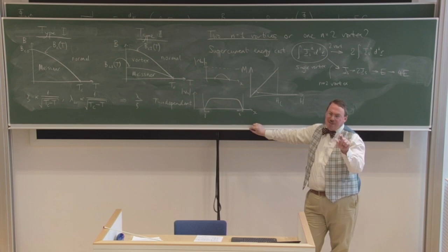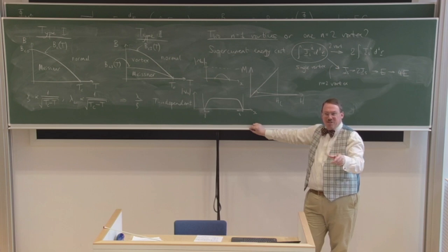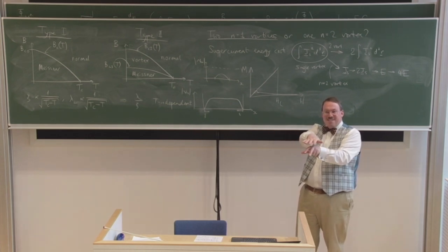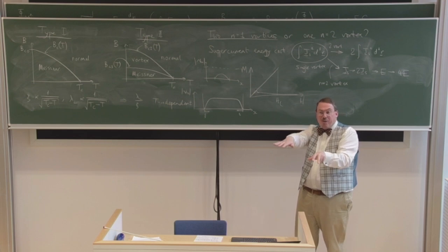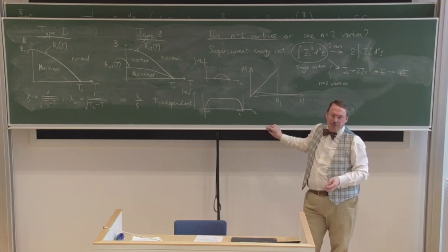I know in cuprates, for example, even when you have a cuprate doing a vortex phase, the vortices don't really stick together from one layer to the next. And so you lose this idea of having a cylinder going through the whole sample. You have kind of 2D vortices that swim around. They have a slight tendency to stick to each other, but actually it's not that great, and you can get into phases where they're wandering independently. But that sort of argues against the point you were speculating about, that you simply can't have 2D superconductivity.